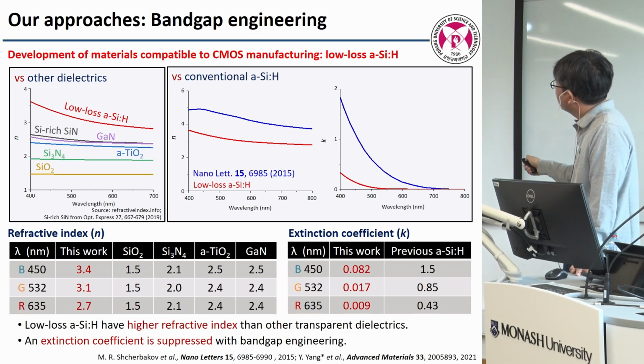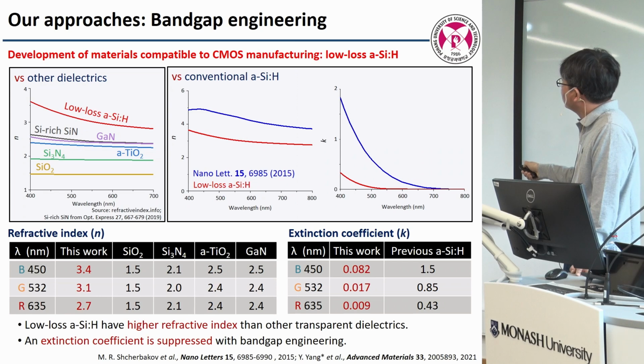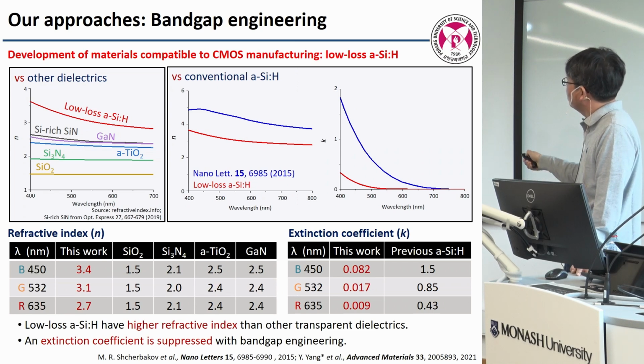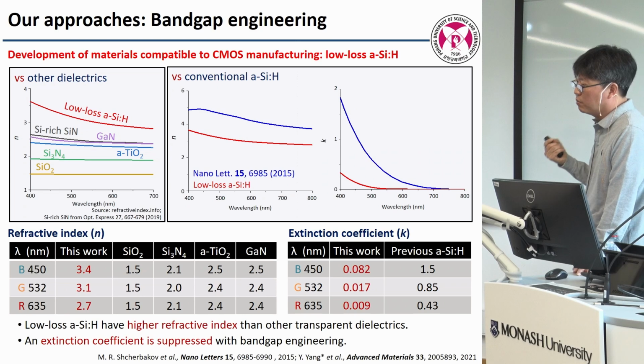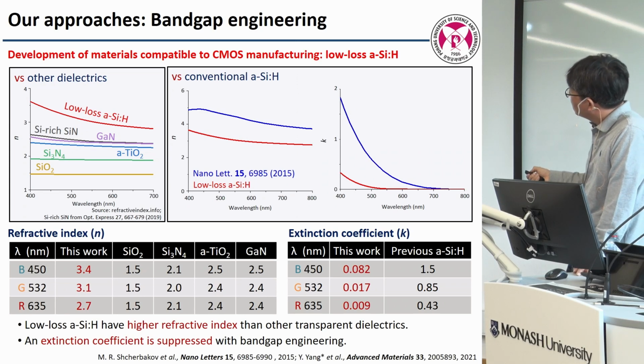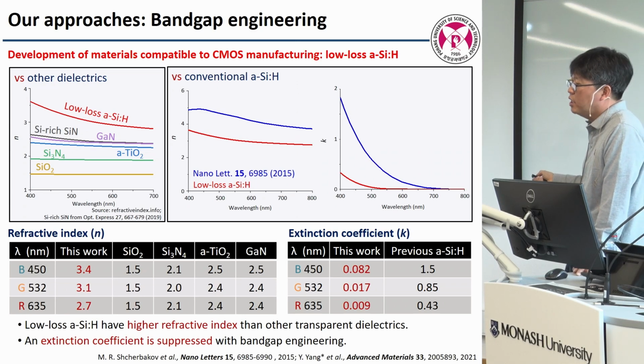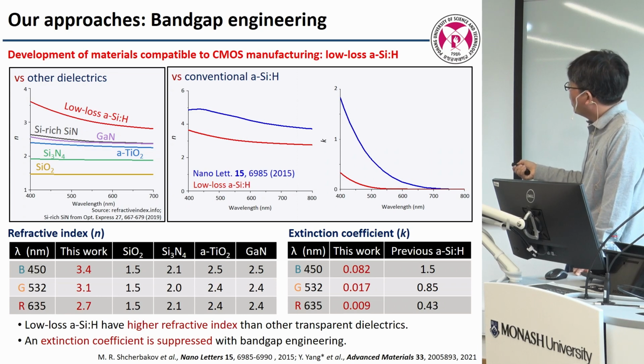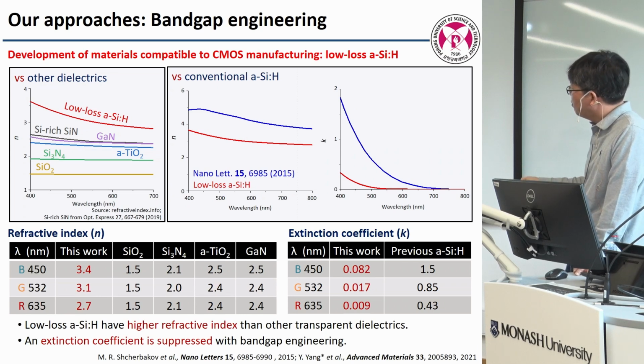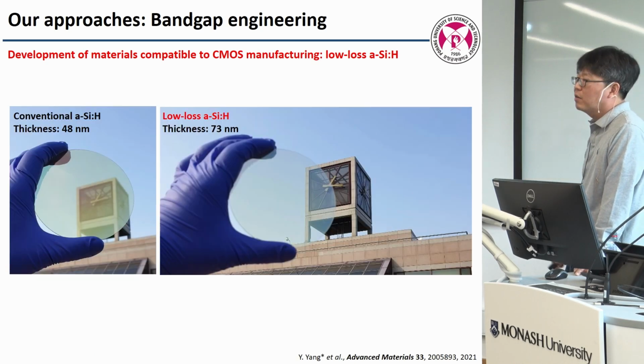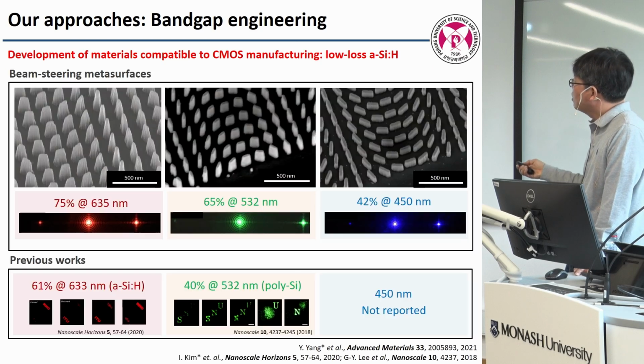This is a typical CVD silicon, high n, but very high K in the visible, so it is opaque in the visible. But this red line is a new engineered silicon, a little lower n, but still comparable to TiO2 and gallium nitride. And K is compressed to almost 0, which means it is transparent in the visible. And then we can use silicon to control RGB, full control of the visible wavelengths.